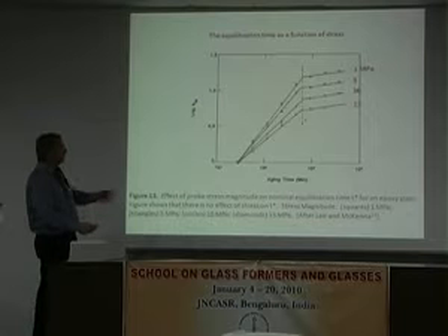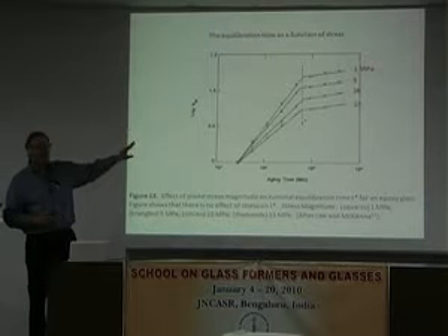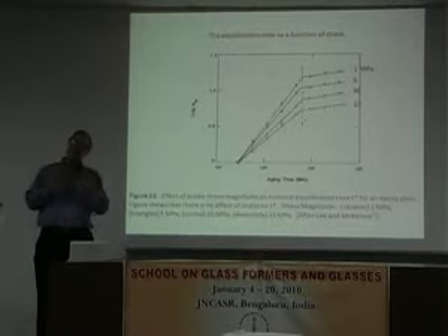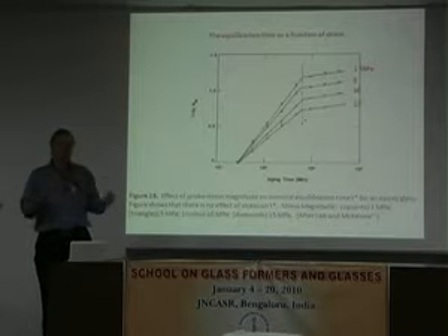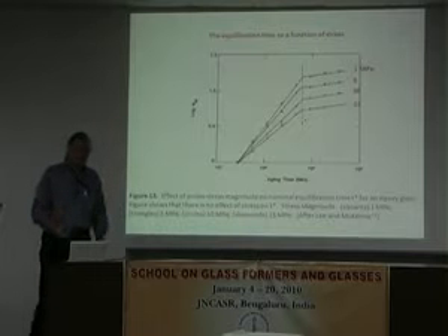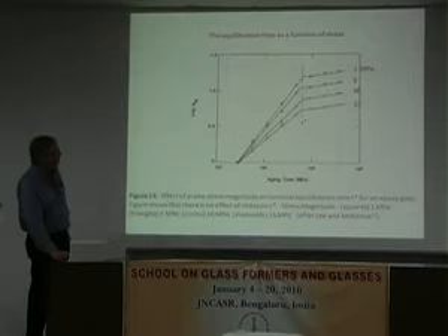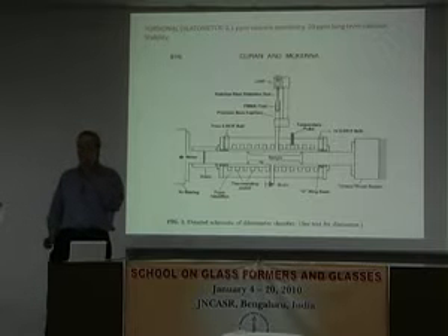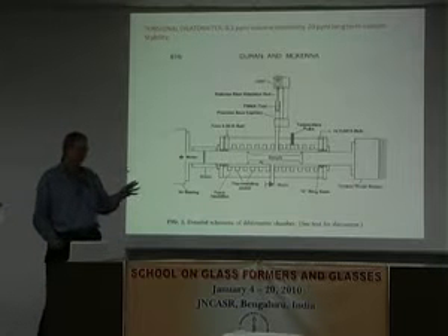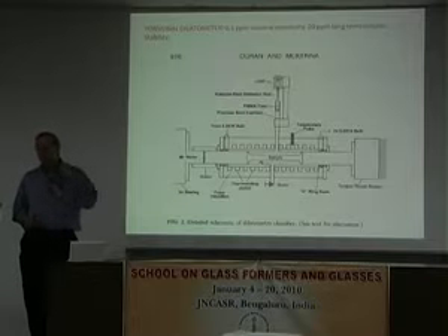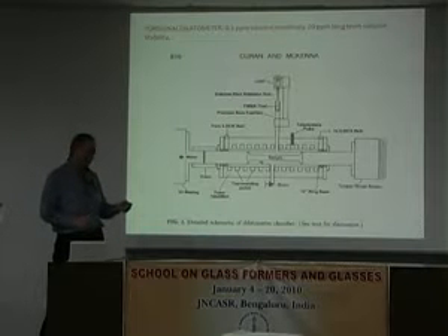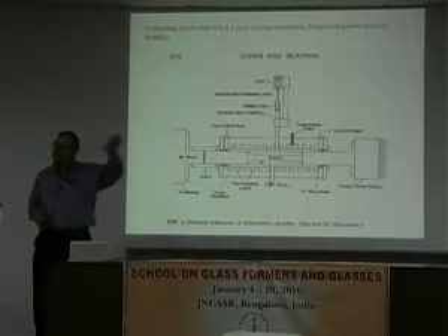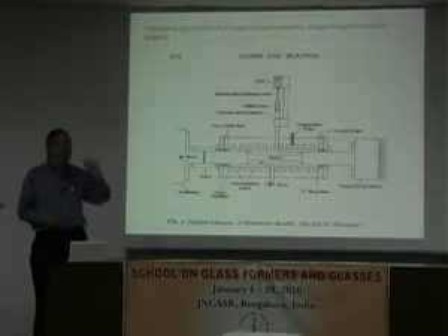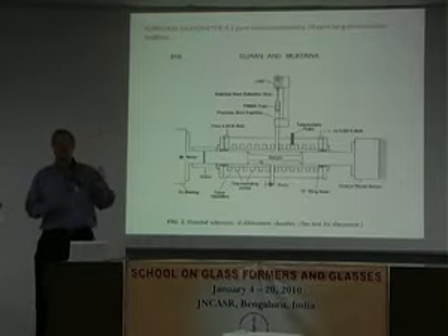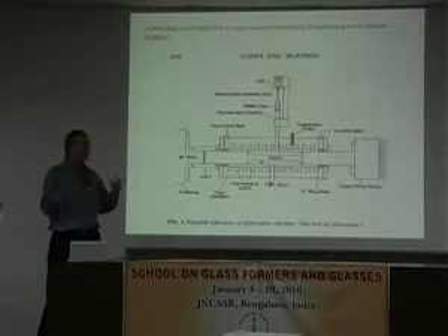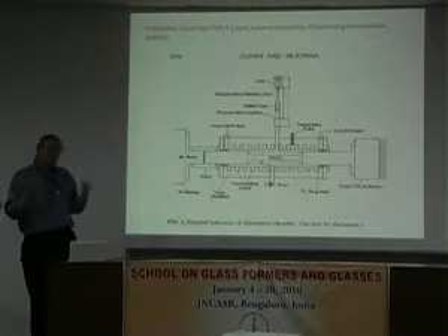But of course, this is sort of kludgy as a way to look at things. And so we really wanted a direct measurement of a thermodynamic type variable, which would be the volume. And so we designed a torsional dilatometer. And you know what a dilatometer is, right? It's something to measure volume. Okay? And what we wanted to do was the mechanical measurements and the volume measurements simultaneously. Now, if you remember the structural recovery behavior, we were only looking at strains, or volume changes, of something like 10 to the minus 3, 2 to 3 times 10 to the minus 3.